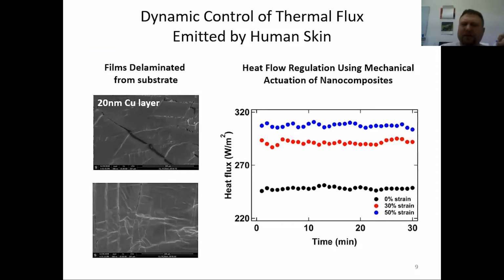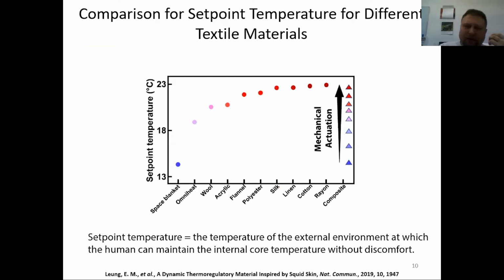Additionally, the nanocomposites need an estimated input of about 3 watts per square meter for mechanical actuation switching. The nanocomposites do not consume power continuously, making their energy requirements substantially lower than all other active thermal management platforms. So, these materials, in their initial relaxed unstretched state, feature a set point temperature of about 14.5 degrees Celsius, similar to that of, for example, the space blanket, which is a static platform that does not have the capability to dynamically change the amount of infrared radiation reflected or transmitted.